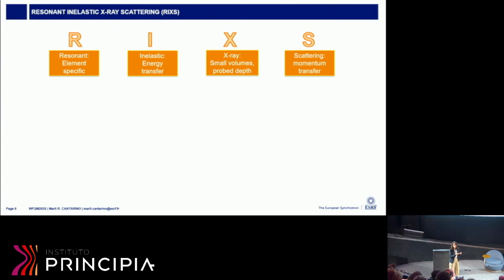Because of that, we have the particularities of light-matter interaction and also different penetration depths, but it also allows us to do this technique in small samples, small volumes and thin films, which is not possible for inelastic neutron scattering. And it's a scattering technique because we use the geometry of the experiment to probe the momentum transfer to the system, so it's also a momentum resolved technique.